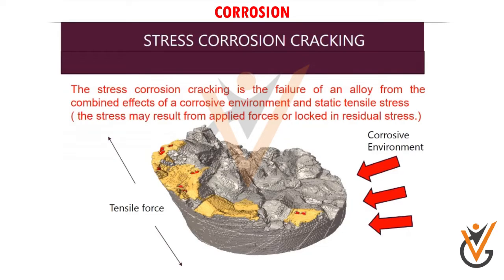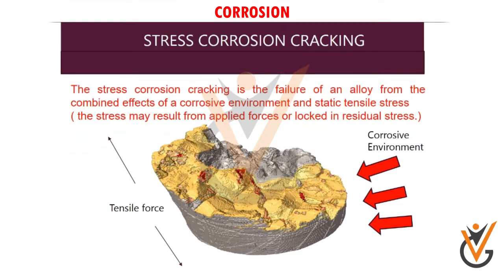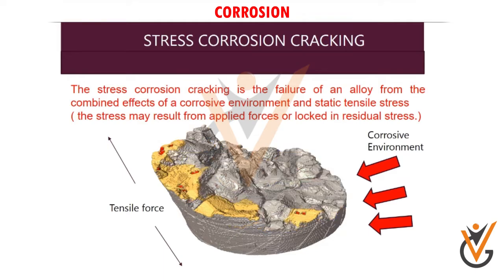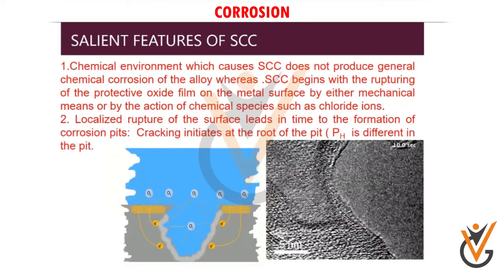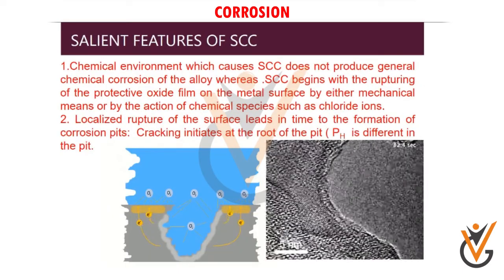Stress corrosion cracking (SCC) is a result of the combination of tensile stress and a corrosive environment, often at elevated temperatures. It may also result from residual stress imparted during the manufacturing process, such as from cold forming, welding, machining, or grinding. In stress corrosion, the majority of the surface usually remains intact; however, fine cracks appear in the microstructure, making the corrosion hard to detect.